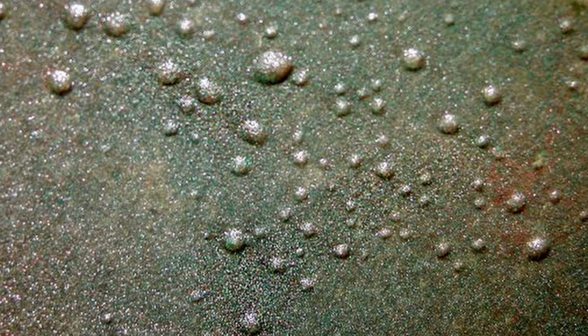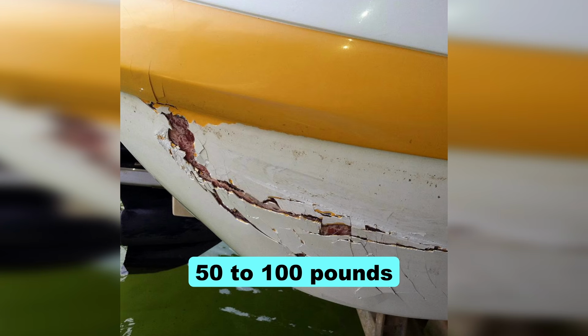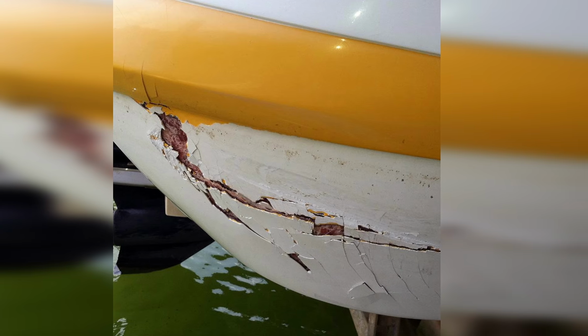The pressure builds and builds. This osmotic pressure can reach 50 to 100 pounds per square inch. That's enough to physically rip the gel coat away from the laminate underneath. The result is what you see on older fiberglass boats.